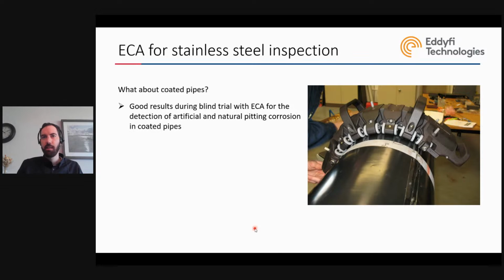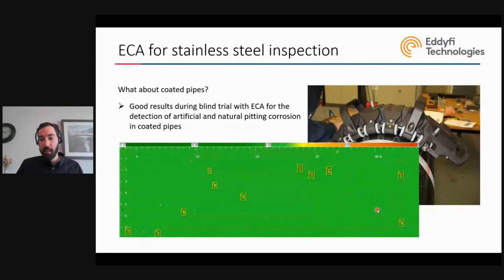We've also investigated if we could detect pitting on top of a coating. So here you have a very smooth coating of about 3 millimeters on top of a stainless steel pipe. And just the same way, the nice advantage of eddy currents is that you can inspect through coating. So the magnetic field will propagate through the coating, and you'll be able to detect those pitting through coating. So this was just a very similar type of results where you see all these little red dots corresponding to pitting.